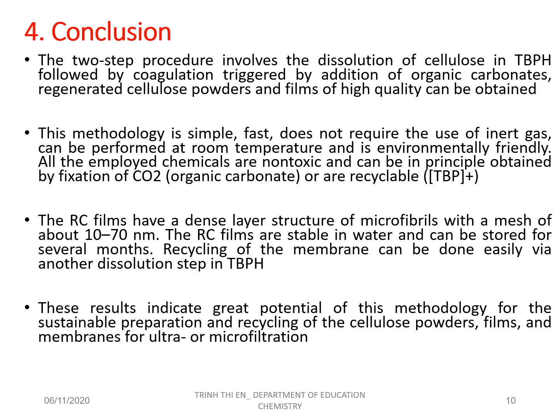This methodology is simple, fast, does not require the use of inert gas, can be performed at room temperature, and is environmentally friendly. All the employed chemicals are non-toxic and can be, in principle, obtained by fixation of carbon dioxide, organic carbonates, or